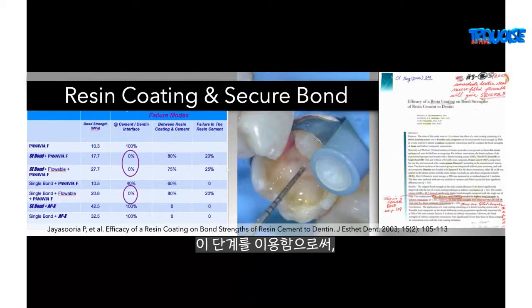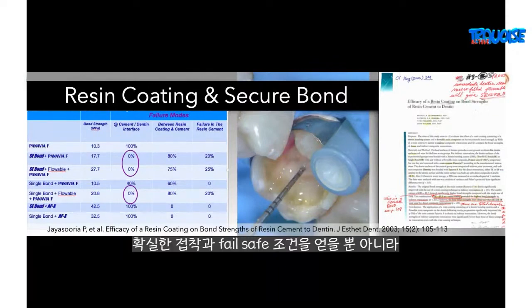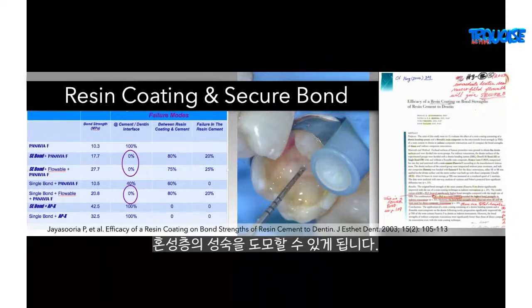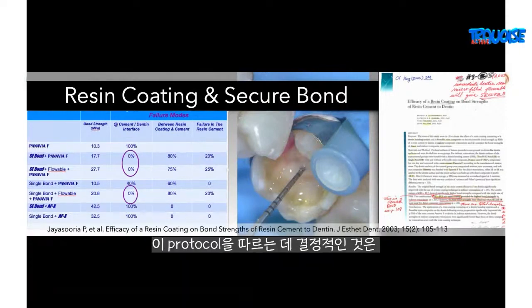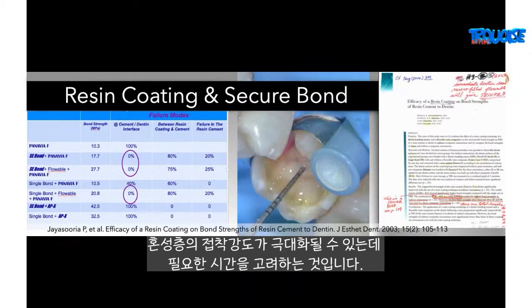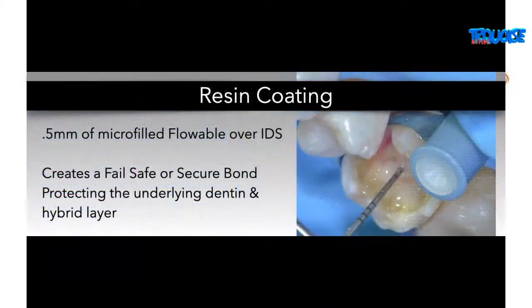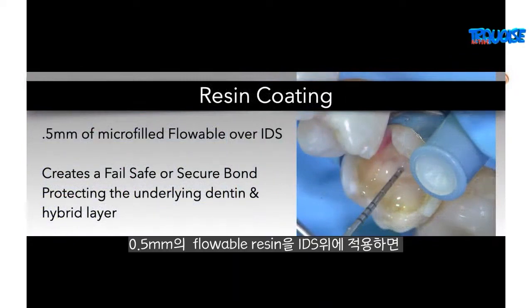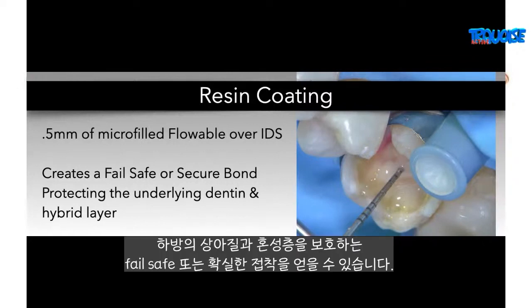But by using this step, not only do we promote this secure bond or fail-safe condition, but we also allow the maturation of the hybrid layer. Very critical in following these protocols is considering the time it takes for the hybrid layer to maximize its bond strength. So we use a 0.5 millimeter of microfilled or a nanohybrid filled flowable over the IDS. It creates a fail-safe or a secure bond, protecting the underlying dentin and the hybrid layer.